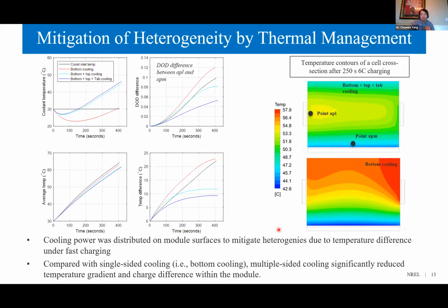Compared with bottom cooling, bottom and top cooling reduce the temperature and the depth of discharge difference within the module by 10% and by 10 degrees Celsius and 4% respectively at the end of 6C constant current fast charging. With additional tab cooling, which is more like spot cooling, the depth of discharge difference can be further reduced by 3%.